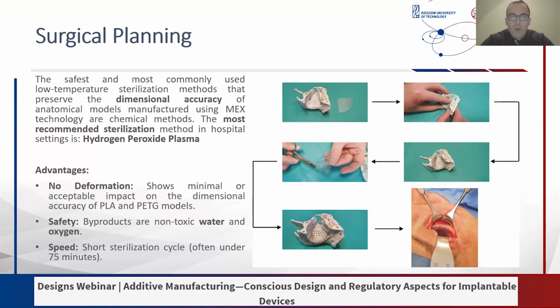When we cooperate with the surgeon, we have analyses. What I said earlier, I don't present in this presentation because the article is under review. But after this analysis, we chose the appropriate low temperature sterilization method, hydrogen peroxide plasma. The advantage of this method is that it does not cause so much deformation of the 3D printed model. This sterilization process is safe, and the short sterilization cycle is also an advantage. The surgeon now uses this model to create the final shape of the titanium mesh.